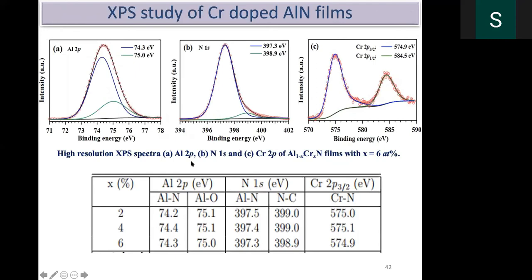Again, we did the XPS study. Here also, the oxygen content is very, very small compared to the aluminum nitride formation. And similarly, the carbon is very low. We can understand this from the nitrogen profiles. And chromium nitride, of course, formed. I just missed the 0 case because that is pure aluminum nitride, which I showed in the previous slides. So I am showing only the addition of chromium. You can find these are all almost close to 575. That means chromium nitride also exists in the system.